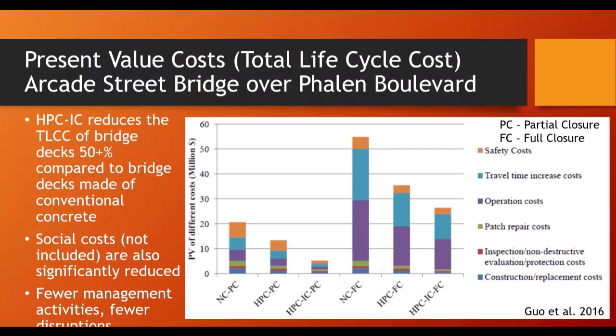The first column is our normal concrete with a partial closure. Second one is our high performance concrete with a partial closure, that middle mixture. And our third one is the internally cured concrete with a partial closure. If we do the three columns on the far side, it's again the same three mixtures, but they're fully closing the bridge to replace it.